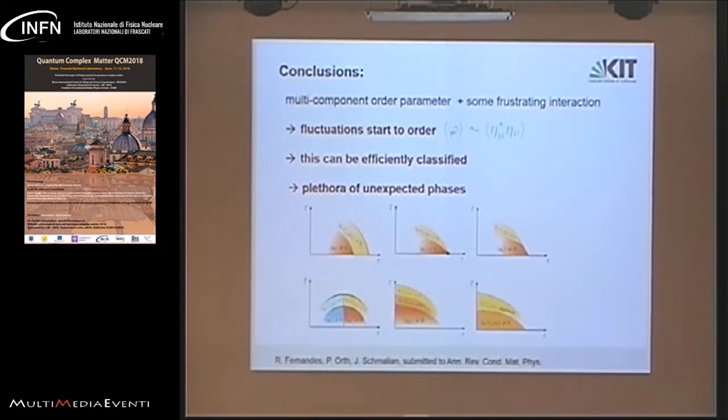First statement about iron selenium. Iron selenium is a funny system because here the primary order parameter, if the story I just presented to you is correct, is hesitant to order itself, right? But that is presumably not because the system is in any way two-dimensional, and there's some Mermin-Wagner theorem suppressing that order. There are many reasons that this is not the case. In my view, it is probably because the system is more in a strong coupling regime than many of the other iron-based superconductors. If you look a little bit, you get that vestigial phase when you have a threshold correlation length of the primary order parameter.